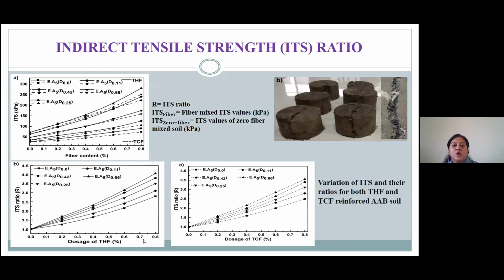We go to the ITS, the indirect tensile strength. It was carried out in a Marshall stability apparatus by attaching a loading strip of around 12.5 mm on the load frame, and we used a constant strain rate of around 50.5 mm per minute.